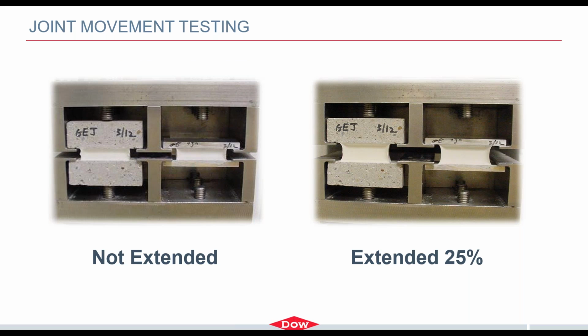The next couple of slides are just some pictures from the lab to give you a visual of what's going on during some of these tests. So this slide and the next slide are C920 spec tests, and this is the joint movement testing where we have a dried joint, which is in the joint tester here, and then it gets cycled over time at various temperatures. And here's a picture of it extended by 25% from the initial width of 0.5. So these are class 25 joints.